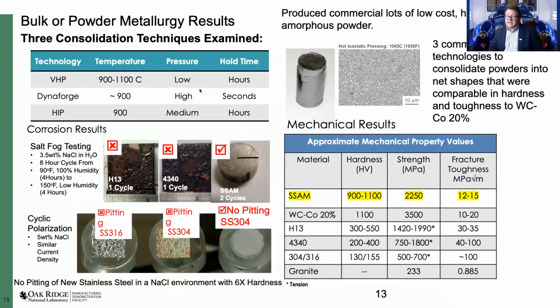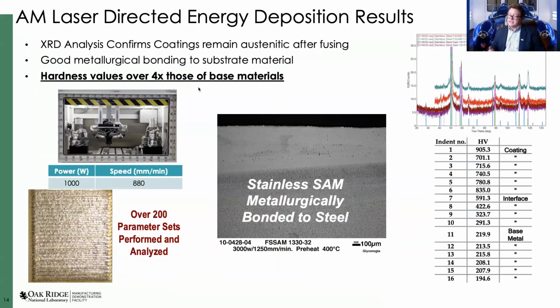We also did salt fog tests to compare this to some of the tool steels you may look at, like 4340 and H13. On top of that, we really wanted to look at the fracture toughness and hardness. In these cases, we compared it to a higher cobalt percentage, like 20% cobalt tungsten carbide cobalt, and found that we could get hardness values in league with the tungsten carbide cobalt, along with fracture toughness that was close. They're slightly more brittle than you would expect with the tungsten carbide cobalt, but some really interesting materials. The overall interest, though, was taking those materials and seeing if I could bond them and get a metallurgical bond, so very intact, and fuse these materials down onto steel substrates.